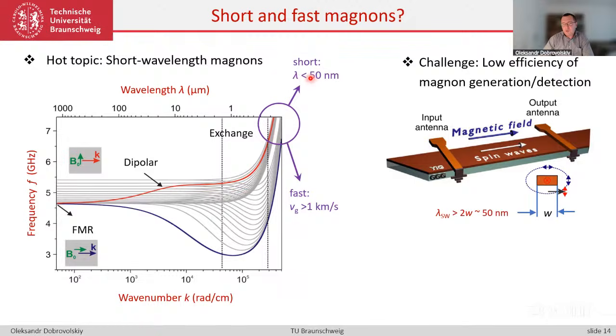We are talking about wavelengths of the order of a few tens of nanometers, because we want to develop and to operate with nanoscale magnonic devices, which themselves are small, so the respective building blocks, magnons or spin waves, should be characterized by respectively short wavelengths. But because of the shape of the dispersion characteristics, you see here, because of the parabolic dependence, also the derivative, this curve becomes very steep. And this means that also the group velocity is very fast, and we are in the kilometers per second range. So there are two major characteristics of exchange-dominated spin waves. They are characterized by short, so nanometer scale wavelengths, and velocities of the order of kilometers per second or even more.